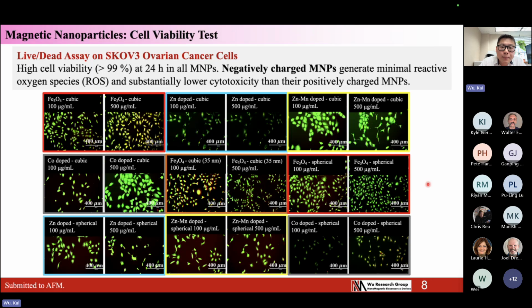So based on all the 9 particles we tested at 2 concentrations, we can confirm it has over 99% cell viability in this testing over 24 hours of incubation. Which tells us that the negatively charged MNP surface generates minimal ROS, which is the reactive oxygen species, which lowers the cytotoxicity of these particles to the cells. Okay, so for all the particles we produce, they show very high biocompatibility with the incubation with the cells.